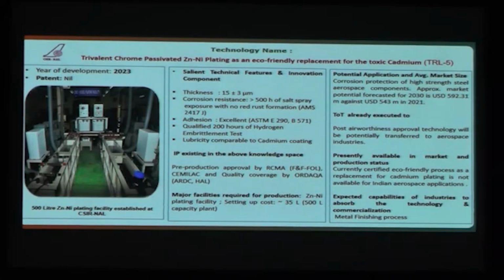The corrosion resistance is more than 500 hours of salt spray without any kind of red rust formation, which is as per the requirement of AMS 2417J. And adhesion is excellent. It has been evaluated as per this standard, and it has qualified more than 200 hours of hydrogen embrittlement test, and the lubricity is comparable to cadmium.